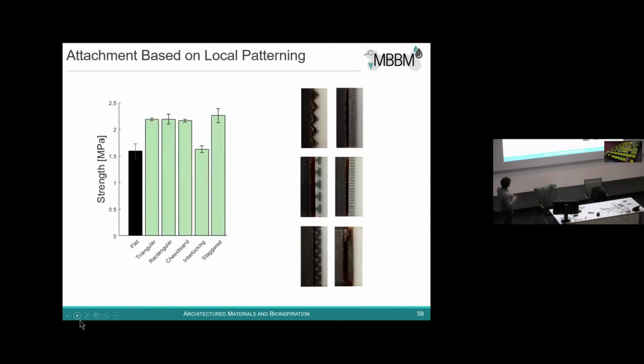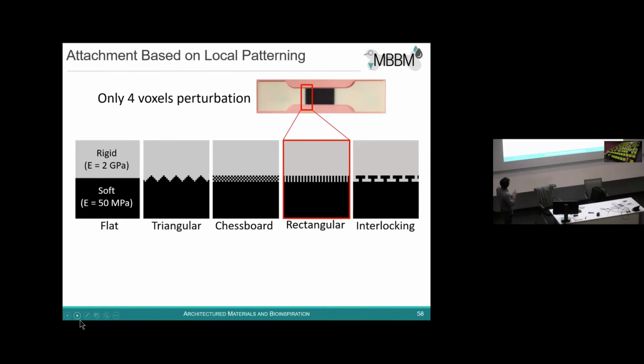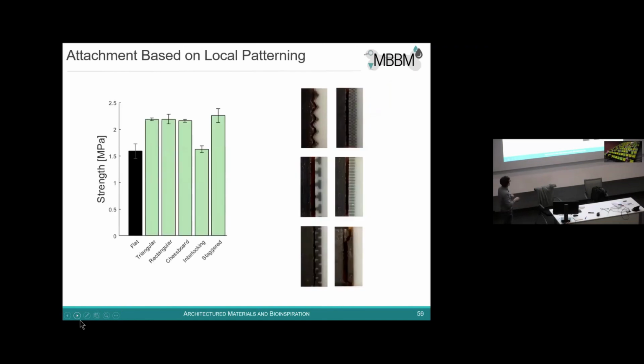And we see that here, for example, the system will be 300 voxels in length. We change only 4 voxels. Each voxel has a dimension of about 400 micrometers. And what we see is that just by changing these 4 voxels with respect to a flat interface, we have an increase of more than 30% or so in the failure strength of the system. And this is something that we are currently working on.